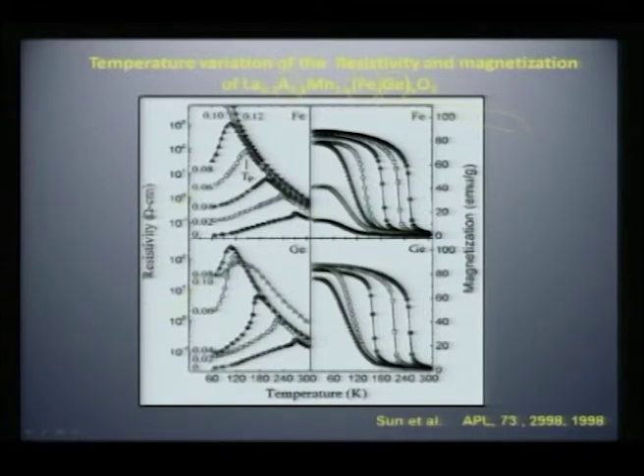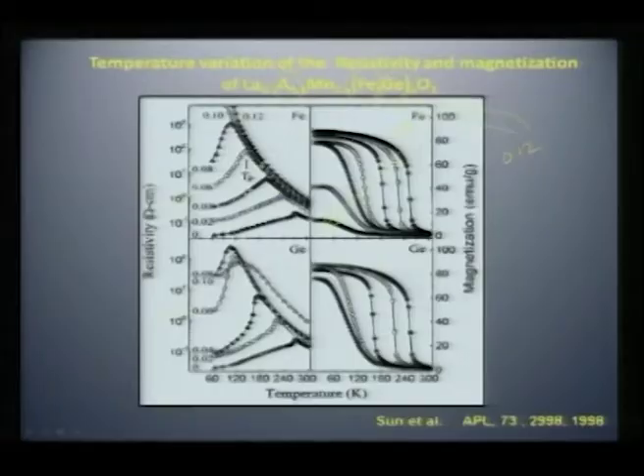As you see here, when you dope iron starting from the parent compound, you can clearly see that the Tc decreases as a function of iron, and the concentration up to 0.12 iron, which means just 12% of iron substituted in manganese, almost kills the ferromagnetic ordering.